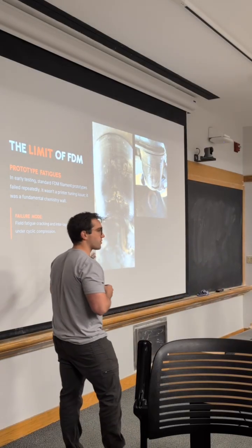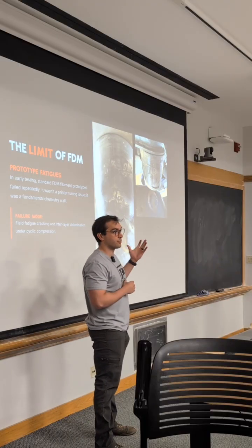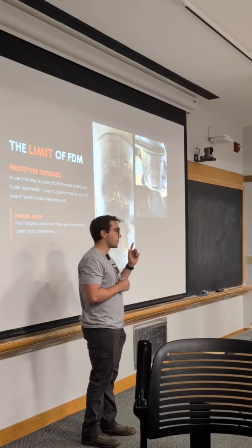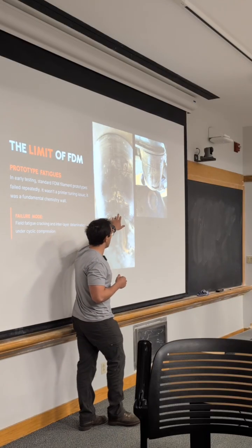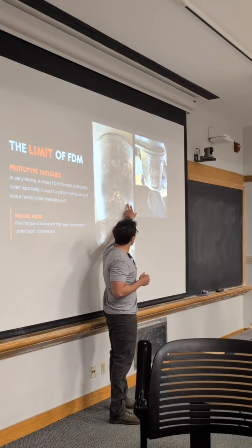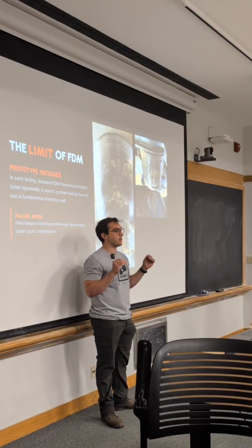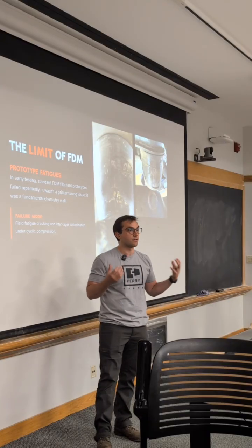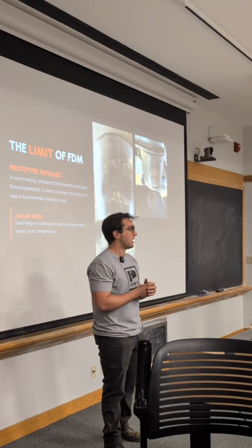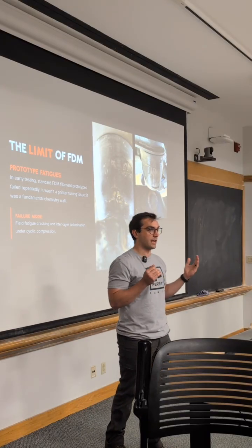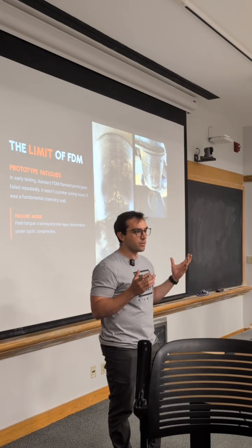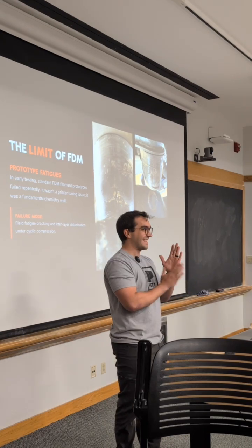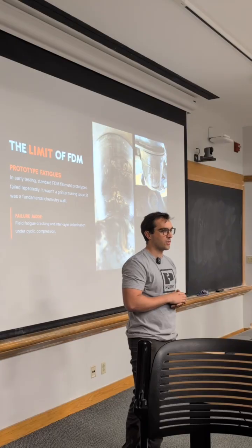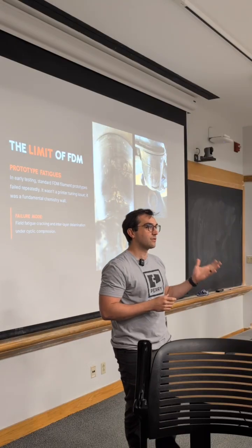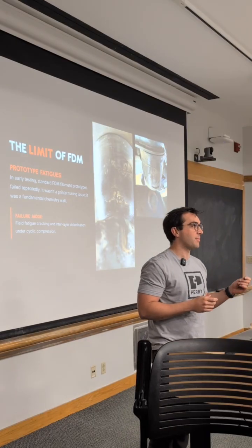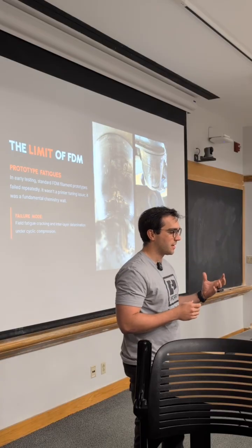So the early prototypes that we made failed pretty reliably. But what's interesting about this failure mode, if you look at it, is yes, there's some failure along the layer lines, which is predominantly the way people think that 3D printed parts fail. They expect delamination between layers. But if you look a little bit more closely, there's also failures against the layer lines, vertically in these parts. That shows us that the material is fatiguing or something else is happening that's causing the material to break down.